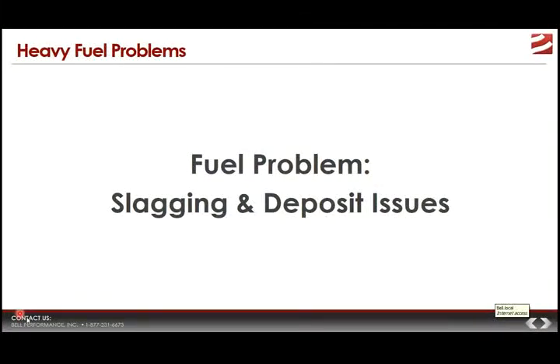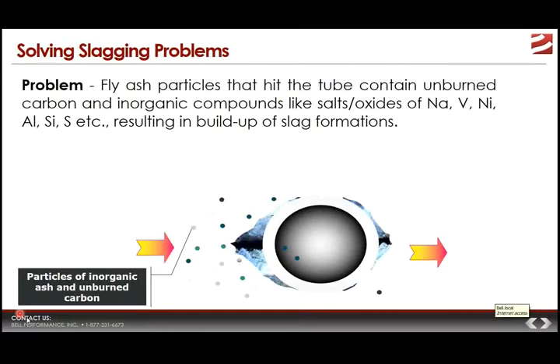So we start by looking at the hows and the whys of slagging and deposit problems stemming from HFO use. The term slagging is a descriptive term describing deposit buildup on tube surfaces. These slag deposits are typically formed from the accumulation of fly ash particles. The fly ash particles that hit the tube contain a mixture of unburned carbon and inorganic elements like salts and oxides of the metals that came from the heavy fuel oil: nickel, vanadium, and sodium, aluminum, silicon, sulfur, those kinds of things.